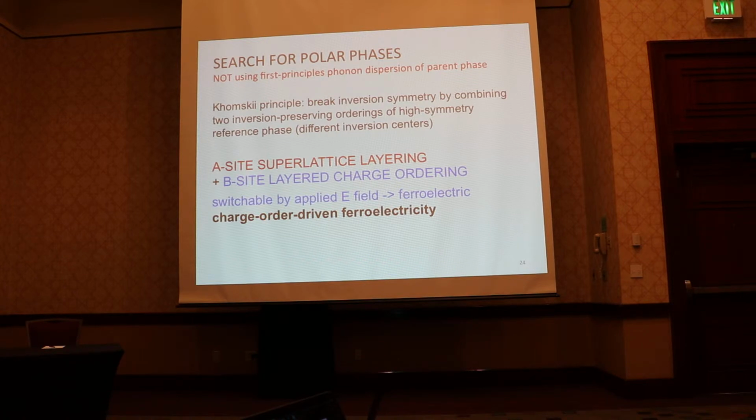I'm just going to mention that there's yet a third way to search for polar phases, which is to use the Khomskii principle and combine two inversion symmetry-preserving orderings of a high symmetry reference phase to get a polar phase. Those can be lattice distortions, but they don't have to be. For example, if you combine superlattice ordering and layered charge ordering, you can get a polar phase which is switchable, and we call that charge order driven ferroelectricity.